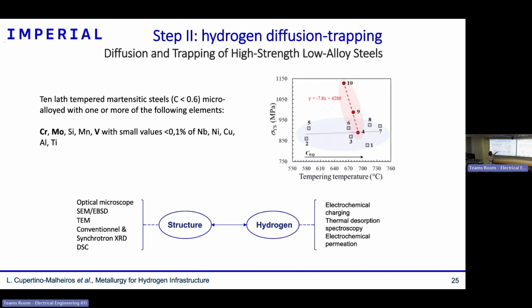which is just the temperature of the last treatment before selling those steels. The yield strength of these steels is mostly related to the tempering temperature and the composition. The steels in red have the same composition, and the strength is mostly related to the tempering temperature: when you heat it up more, it has lower strength. But you can also control the strength by changing the composition, by adding elements like chromium and molybdenum, and that way you get similar levels of strength for different tempering temperatures. This is good because if you heat it up more, you can annihilate some defects.